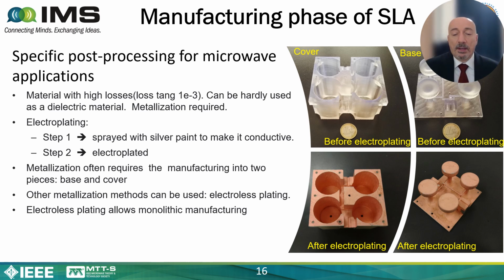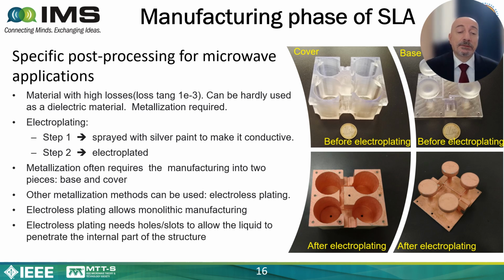That would be very interesting because monolithic manufacturing has so many advantages. You do not have to screw the parts after the manufacturing. It is lighter, and then you don't need to assemble and risk higher losses, because the ohmic contact when you join two parts is not so good. So there are a lot of advantages in doing the manufacturing monolithic, and this is in part possible by using the electroless plating, but unfortunately electroless plating needs in any case holes in the structure in order to allow the liquid to penetrate the internal part of the structure. And this is a disadvantage. So let's say that there are some advantages, but also disadvantages, because through this aperture you can also have leakage.